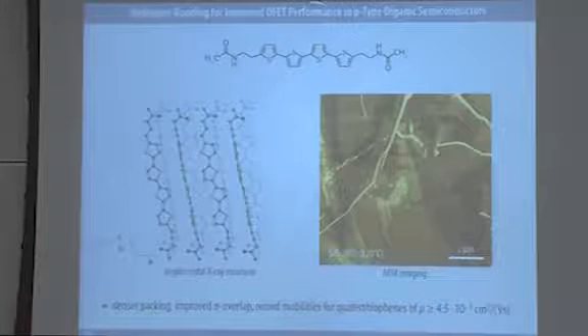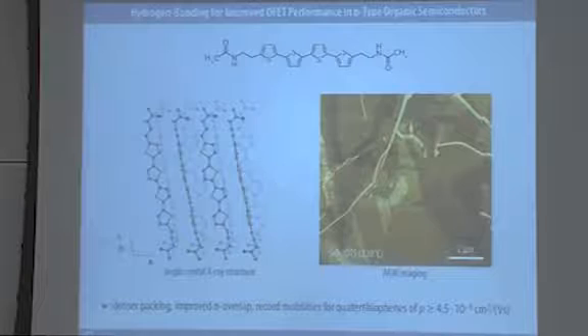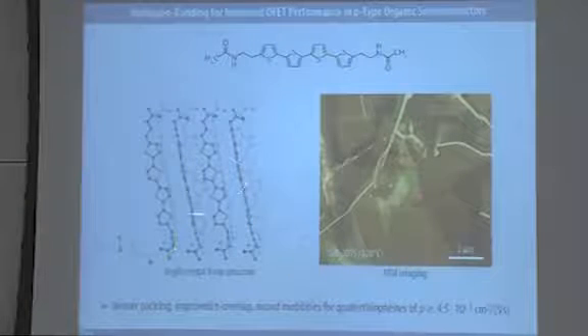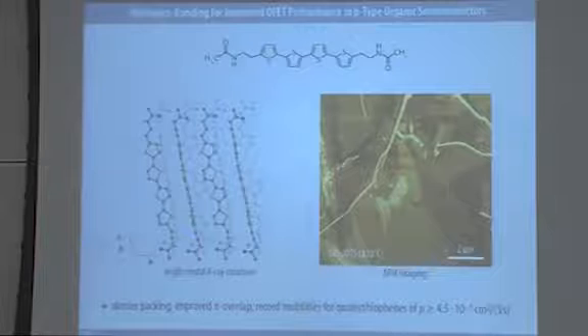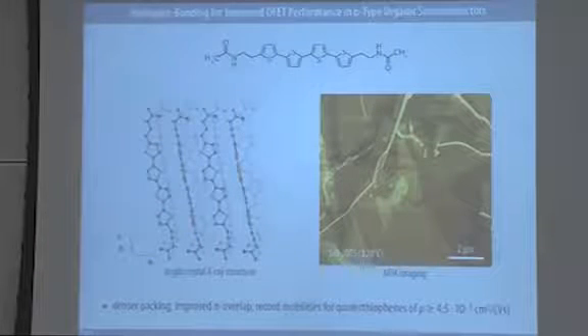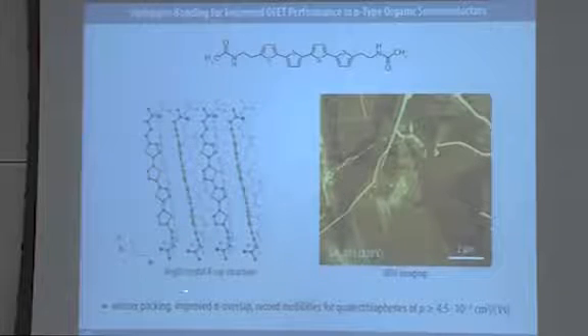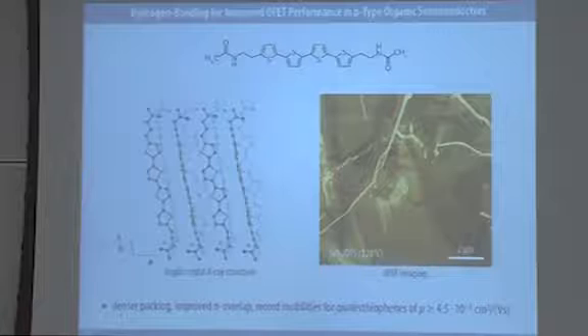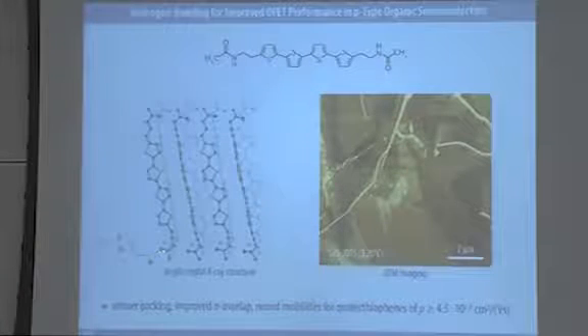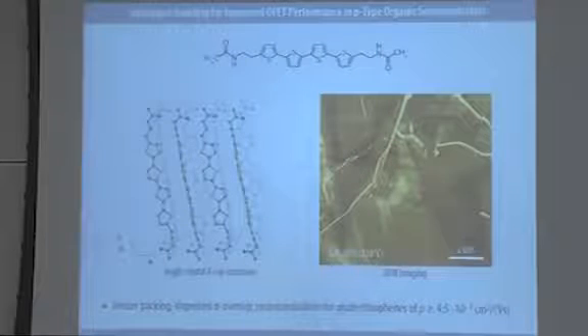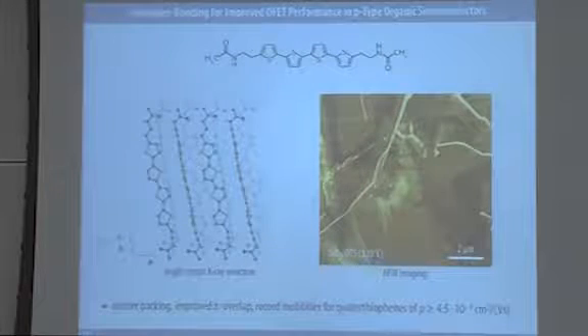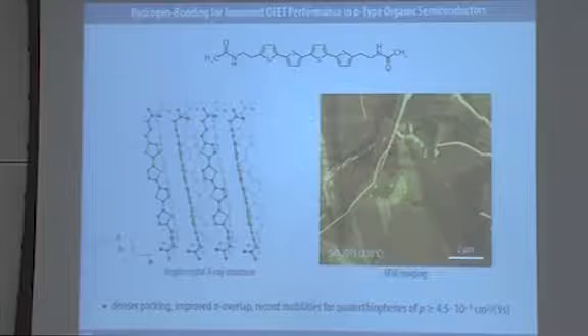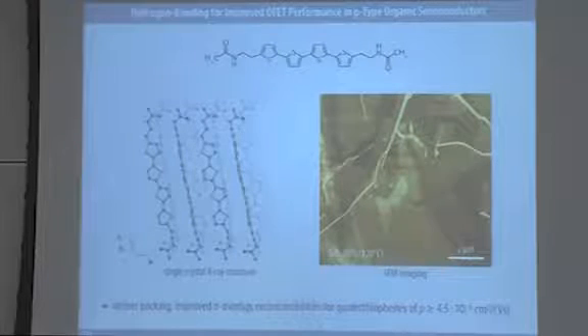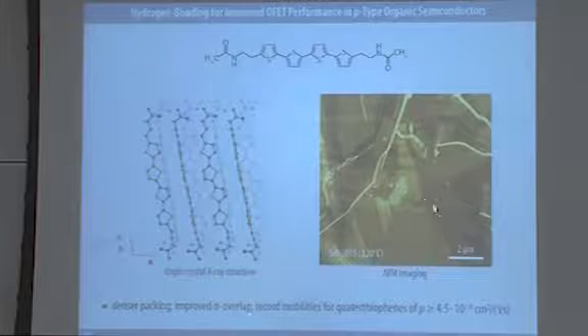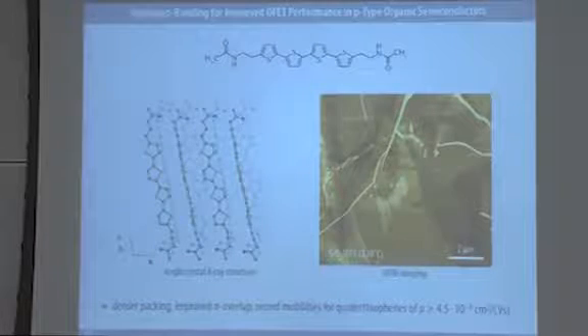So we made these very simple small molecules that crystallize very nicely into a layered structure with a herringbone packing of the pi conjugated segments, very similar to the ones you know from the parent quaterthiophene, or also alpha omega dihexyl quaterthiophenes. However, the lattice parameters are roughly 10% smaller in all directions. Supposedly because the molecules are stitched together by lateral hydrogen bonding. And in collaboration again with Clémence Corminboeuf doing DFT computations, we have been able to show that this leads to improved pi overlap. And not only that, it also helps to grow very nice and large domains of the molecules.